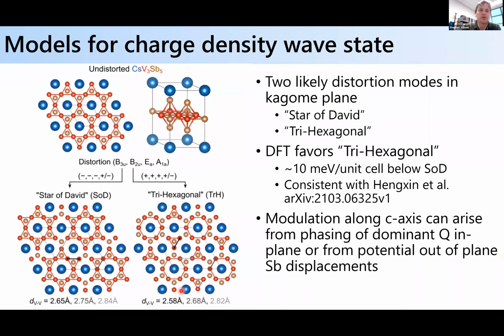Okay, so what are the models for the structural distortion below the charge density wave state? If you start from an undistorted kagome lattice, then some of the more likely models are these different distortion modes: B3u, B2u, Eu, and A1g. These first three are in-plane wave vectors, and if, for instance, they're minus, minus, minus, this gives you a Star of David structure, which is a well-known reconstruction, I think, from people who've investigated this for tantalum disulfide and other systems like this.